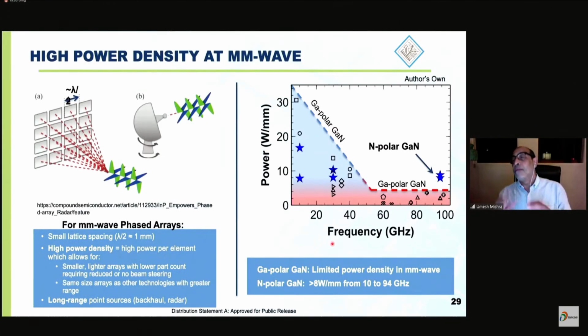Now, why, at millimeter wave, does gallium nitride play a very big role? Because at millimeter waves, when you have an array to deliver power, the distance between elements is about lambda by 2. Since lambda is getting smaller at higher frequencies, you've got to jam. You don't have space to put these elements, and so each element has to put out more power. So you need more watts per millimeter. But what happens is the watts per millimeter from gallium polar devices plummets as seen here. At very high frequencies, you don't get many watts per millimeter, and you definitely don't get it at efficiency.